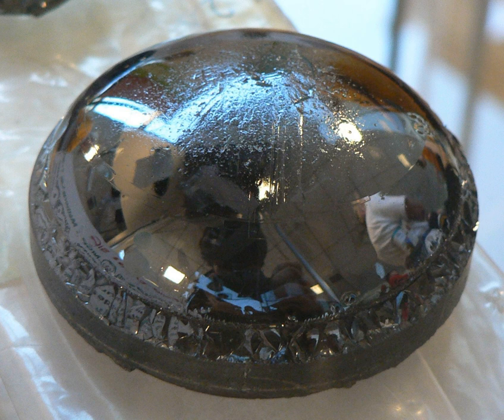Pure silicon carbide can be made by the Lely process, in which SiC powder is sublimed into high-temperature species of silicon, carbon, silicon dicarbide, SiC2, and disilicon carbide, Si2C, in an argon gas ambient at 2,500 degrees Celsius and redeposited into flake-like single crystals, sized up to 2 × 2 cm, at a slightly colder substrate. This process yields high-quality single crystals, mostly of 6H phase, because of high growth temperature.